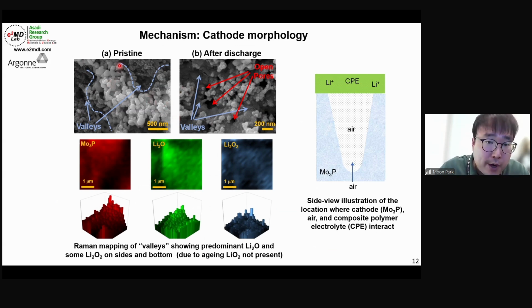Comparing the SEM images, we found that the valleys, the pore sides, are kind of filled, and we assumed that this could be discharge product. Then we did the Raman mapping. From the Raman mapping results, we found that Mo3P, this black area, is lower in height, which means it could be a valley on the surface of the cathode. It looks like the lithium oxide has filled that valley well, and there is also some lithium peroxide. So we try to explain and understand the mechanism of how the discharge product grows.